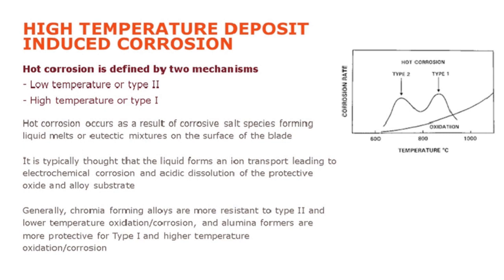So I was just going to introduce high temperature deposit induced corrosion, or hot corrosion, because it's not necessarily that well known about. It's typically defined by two mechanisms: low temperature or type 2 hot corrosion, and high temperature or type 1 hot corrosion. You can see on the figure on the right, we've got a fairly linear relationship between temperature and oxidation rate. However, you have these two humps of accelerated damage for type 2 and type 1, with type 2 occurring at slightly lower temperature. The reason we get these two humps is largely due to chemistry. Hot corrosion occurs as a result of corrosive species forming a liquid melt or eutectic on the surface of the blade, and it typically forms due to gaseous conditions and also the deposition of those species.